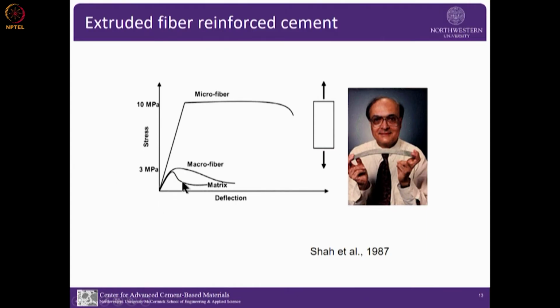So most, as I said, macrofiber is still the most commonly used commercially, but people have been working with this so-called strain hardening cement composite. And here is, for example, one of what we did, which has a 10 megapascal strength and strain hardening response.